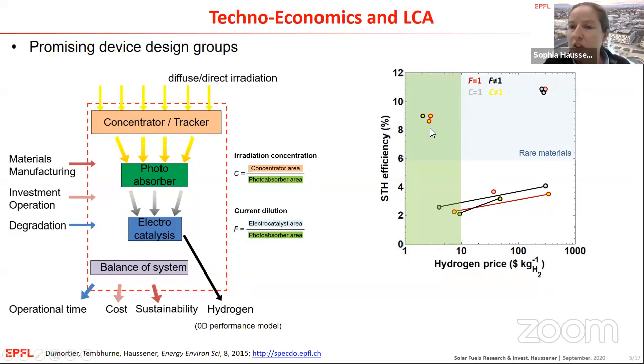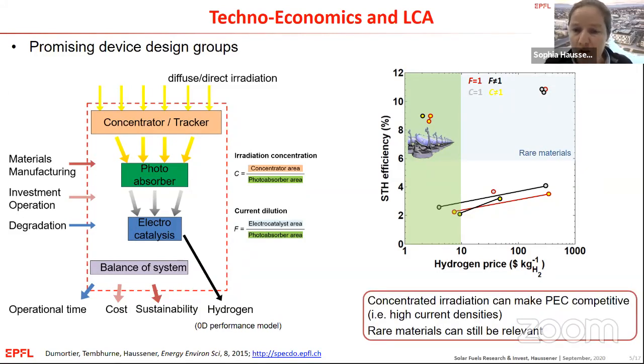These are cases with rather rare materials operating at very high current densities, though, due to the fact that I use concentrated irradiation. So you could imagine this system to look something like this. In fact, later I will show you how we implemented it in detail, but it could consist of such a parabolic concentrator and a receiver in the focal spot, utilizing the high photon flux to convert this into fuel without actually going for high temperatures. So again, what we learned from here: concentrated irradiation can make these PEC devices interesting and competitive, and that mostly is a result of the higher current densities and power densities of these devices. And then also that rare materials can potentially still be relevant if the performance benefit is large enough at these high concentrations and you have reduced the mass of the material by a factor of 100 or even 1,000.